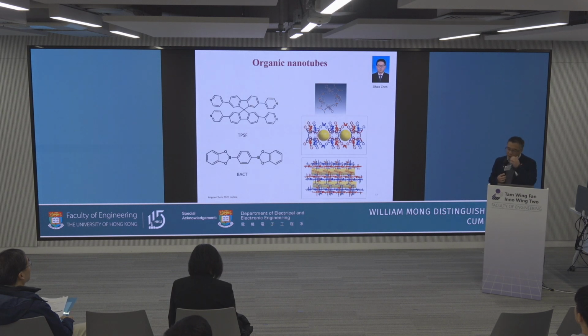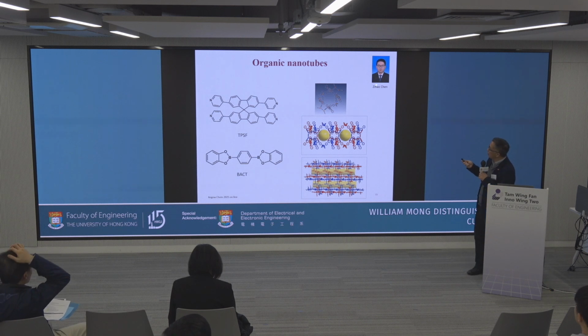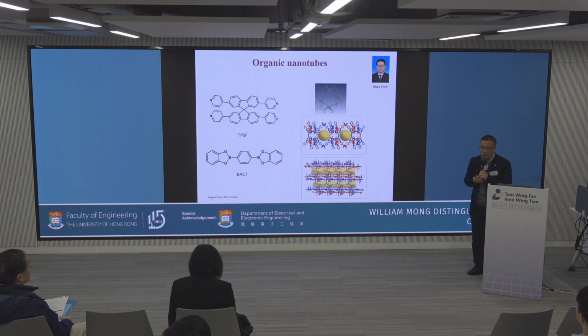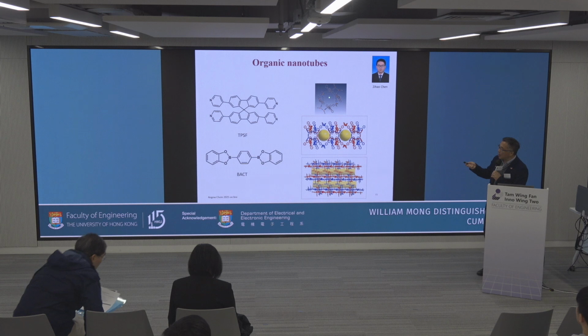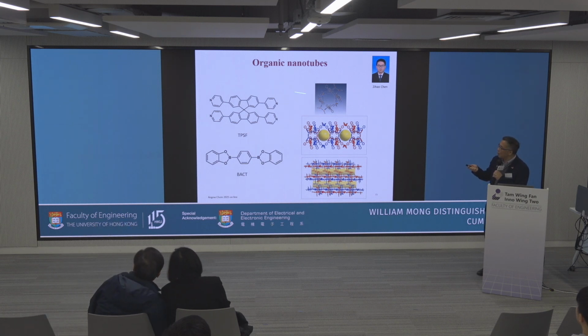Okay. So keep going, and then my PhD student, Mr. Chen Zihao, bought this commercially available compound, the spiral compound. We have the 4-pyridine here, and this 4-pyridine can coordinate with the boron, and then they can form the organic nanotube first. We can see the 3-dimensional framework. Inside, we do have the organic solvent. However, if we try to remove the organic solvent, this structure will collapse. So initially, we tried to use this tube to do the separation. However, we cannot keep the structure. So later on, we still use this material for the lithium metal protection, and it turned out it works very well for the lithium-ion battery.